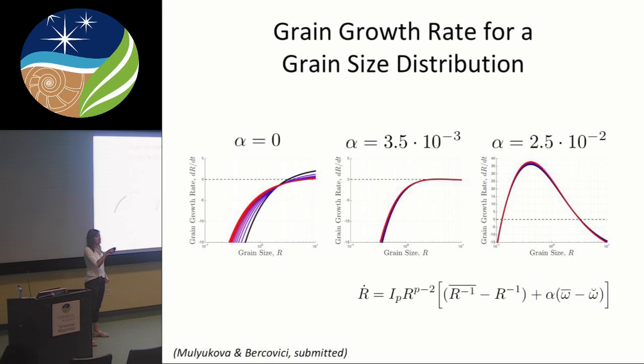Another little side note, also a source of frustration, is that most of the deformation experiments would be done on a grain size range of just a few microns. It can sometimes be within an order of magnitude, so not even a full order of magnitude. So making any form of inference from the broadening and shifting to the right, when you're going from like 2 microns to 5 microns, is difficult. I understand why it's being done, so within some limitations.